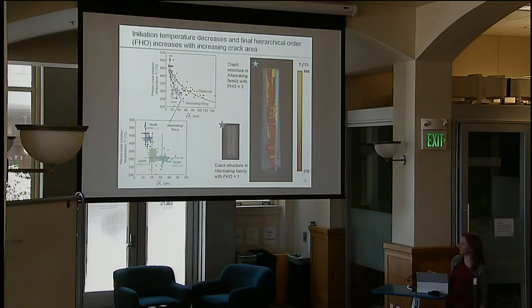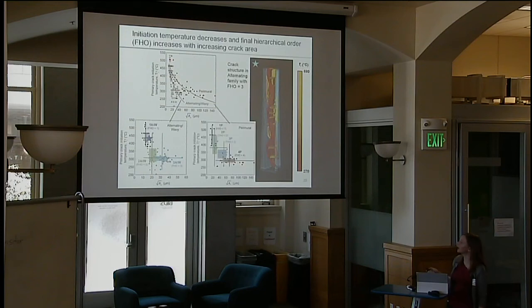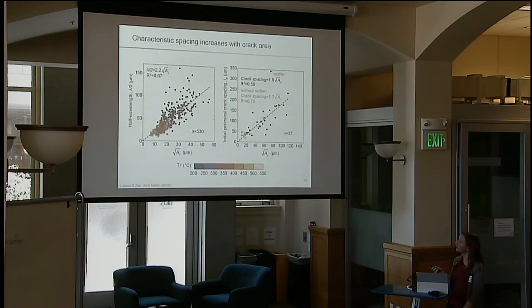So we find that typically the larger regions have a much higher final hierarchical order. And we see the same trend in the perimeral family of cracks. So this further helps us develop models and understand the fracture mechanics. We've also looked at the spacing between the cracks. For the alternating cracks, looking at the half wavelength, and for the perimeral cracks, looking at the spacing. And I found that the spacing also increases with the size of the region. So this also helps us predict more about this 3D crack network that we ultimately want to model fluid flow through.